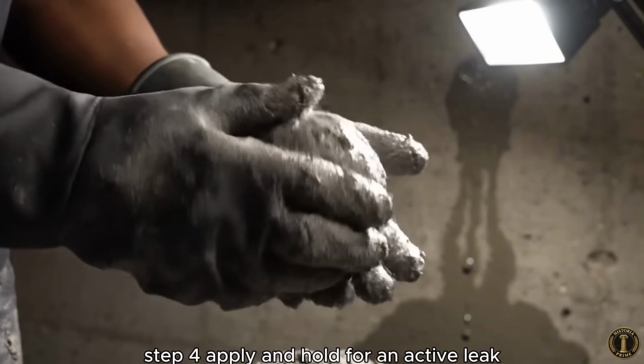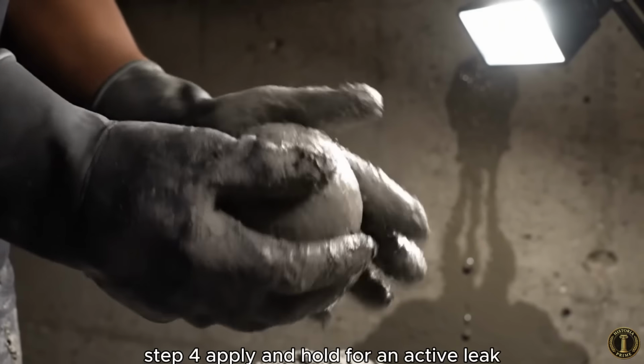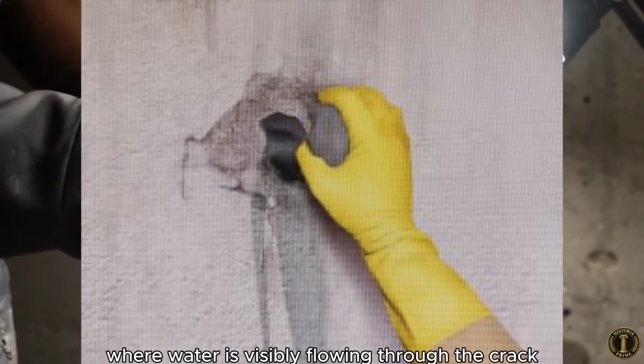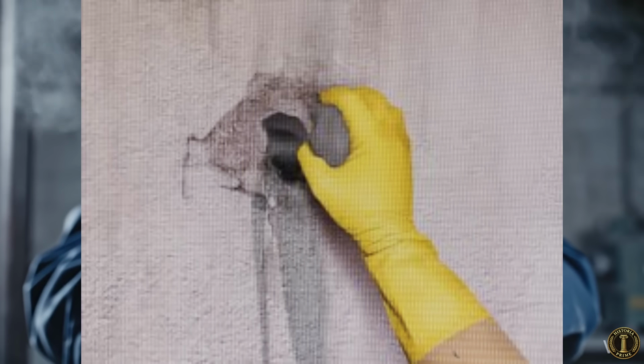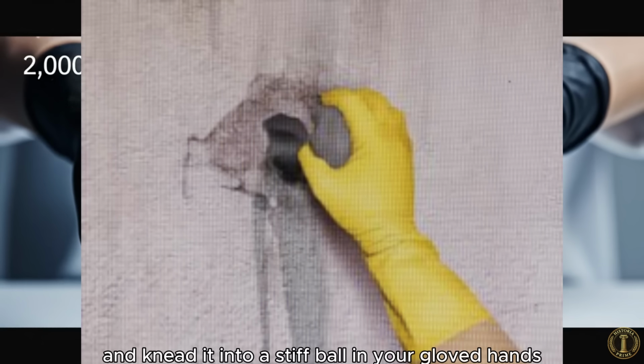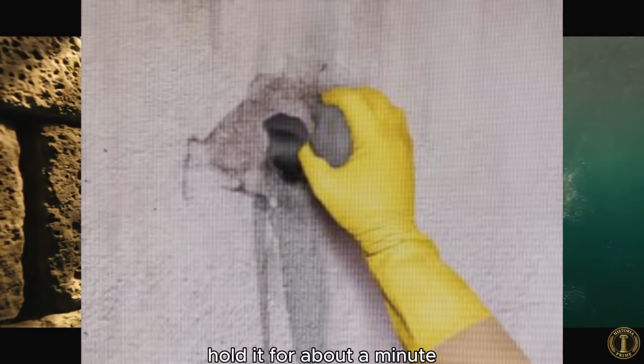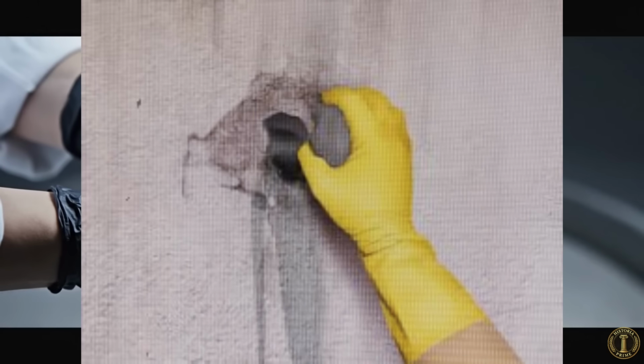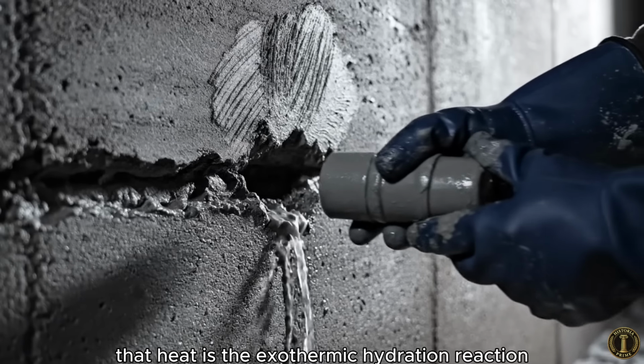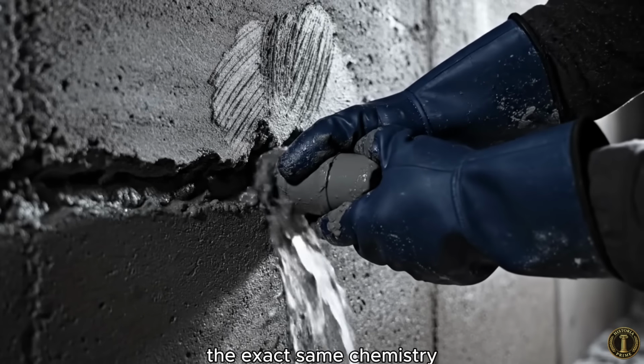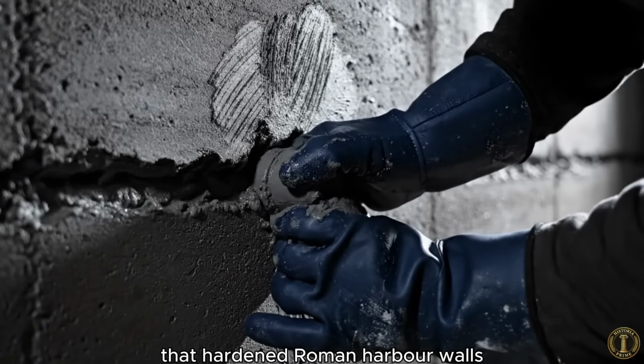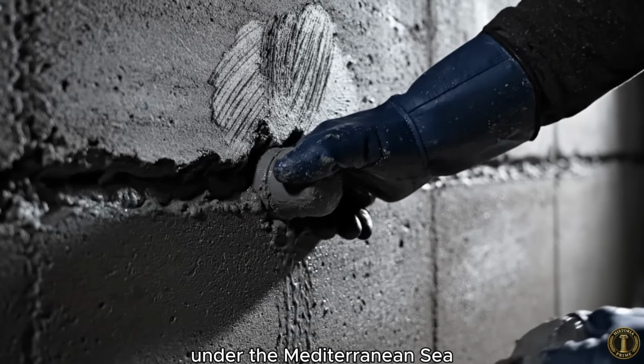Step 4. Apply and hold. For an active leak, where water is visibly flowing through the crack, you will use what is called the plug method. Take your thick mixture and knead it into a stiff ball in your gloved hands. Hold it for about a minute. You will feel the ball growing warm through your gloves. That heat is the exothermic hydration reaction, the exact same chemistry that hardened Roman harbour walls under the Mediterranean Sea.